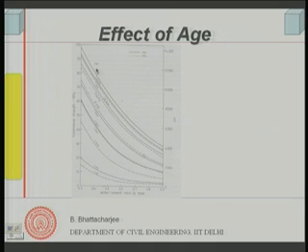Now, there are different grades of concrete, etcetera. Now, why does the strength increase? Because the degree of hydration would be more. In other words, the hydration product filling in the void space would be more. If you remember, when we talked of curing, we said that only through curing do you achieve discontinuity of the pore system, the segmentation of capillaries. What we mean is, a cement particle requires time to actually hydrate. Initially some portion of the cement particle will hydrate and fill in some of the originally water filled space with hydration product, and as you continue the curing process, in other words as the age increases, more and more particles will hydrate and occupy the pore space that was occupied by water before, and therefore there would be an overall reduction in porosity.